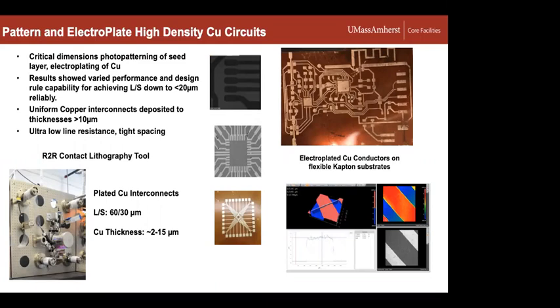We've plated copper thicknesses up to in excess of 10 microns, and you could go further if you had a thick resist. And if we look on the upper right, we show a more complex integrated circuit, all copper, good adhesion on Kapton, and we've assembled devices and components onto this. So it actually is a much better approach if you need high current handling capability, low line resistance. This is going to be in the milliohms, possibly even lower, because it's copper, as compared to a silver ink,